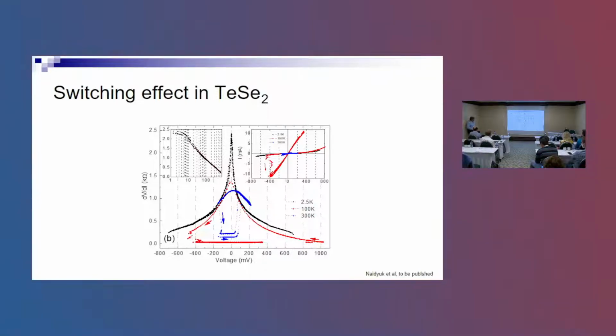And what is interesting, it survives up to room temperature. Of course, it becomes less pronounced. Here you see this is 2.5 Kelvin, the black curve, and the blue one is at room temperature. And the threshold becomes smaller and smaller. A similar effect was also observed in some semimetals like tungsten telluride and molybdenum telluride, which are basically also van der Waals materials, layered materials.